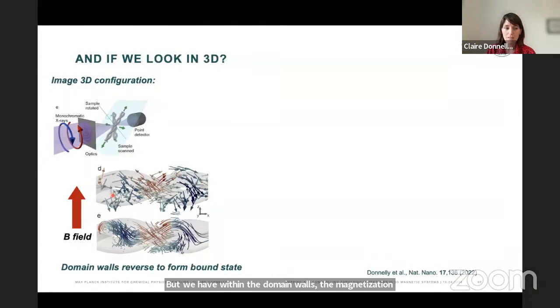And so what essentially we have is these domain walls reversing due to the strong magnetostatic interaction between the domain walls, between these transverse domain walls. Because they are tightly coupled by magnetostatics, what is very interesting is that they form a bound state that is relatively robust to small-ish fields, on the order of 20 to 30 millitesla. So not only do we have this regular array of domain walls, but we have them relatively robust, almost similar to the idea of a synthetic antiferromagnet in magnetic thin films.